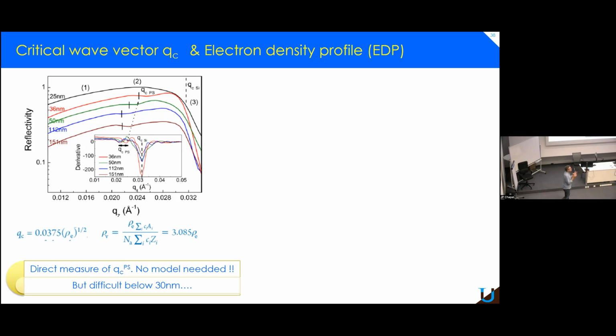But again, to be sure that it's really polystyrene, afterwards we have to anneal to release any stress. The problem with polystyrene is that most of the nanoparticles are cross-linked because they are used in different applications, and if you have a little bit of solvent, they are not cross-linked. So cross-linking them obviously will change the result. But making nanoprecipitation maybe of polystyrene droplets, using the Ouzo effect for example, might be a way to then measure the density of those nanoparticles.